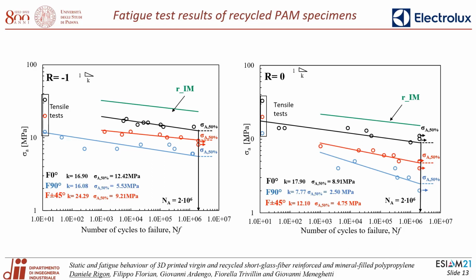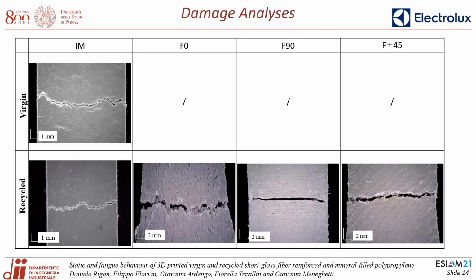The same anisotropy seen in the results of the static tests can be observed in the fatigue curves of the additive manufacturing specimens, where the best fatigue performance is obtained on the F0 specimen, while the lowest fatigue strength is obtained on the F90 specimen. Furthermore, all the AM fatigue strengths are lower than the results obtained on injection molding specimens.